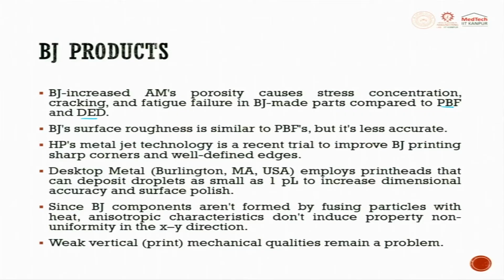HP Metal Jet technology is a recent trial to improve BJ printed sharp corners and well-defined edges. HP has already done this. Desktop Metal employs a printer head that can deposit droplets as small as 1 picoliter to increase dimensional accuracy and surface polishing. 1 picoliter: liter, milliliter, microliter, nanoliter, picoliter. Okay. Since BJ components are not formed by fusing particles with heat, anisotropic characteristics do not induce property non-uniformity in the XY direction. Weak vertical mechanical properties remain a problem even today.